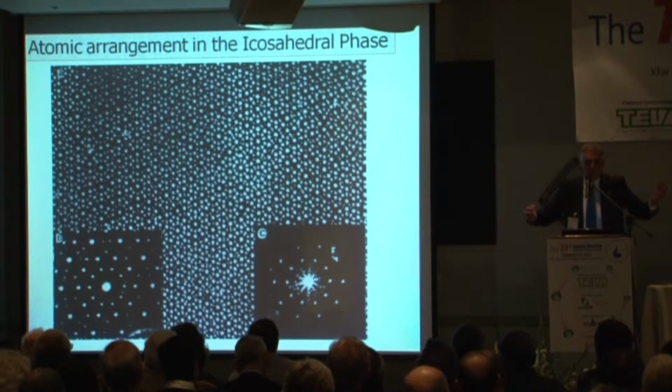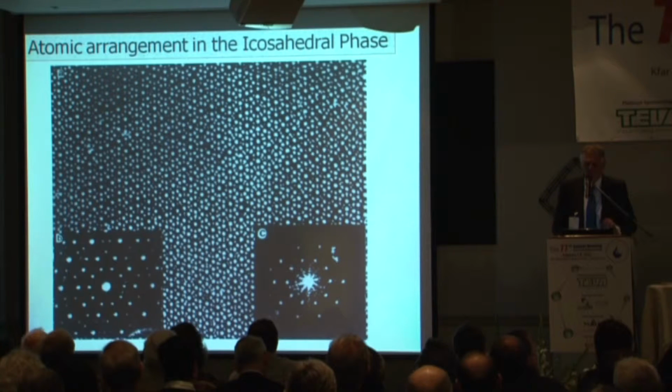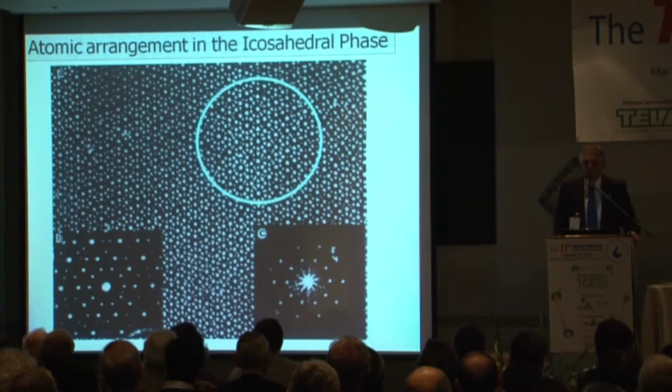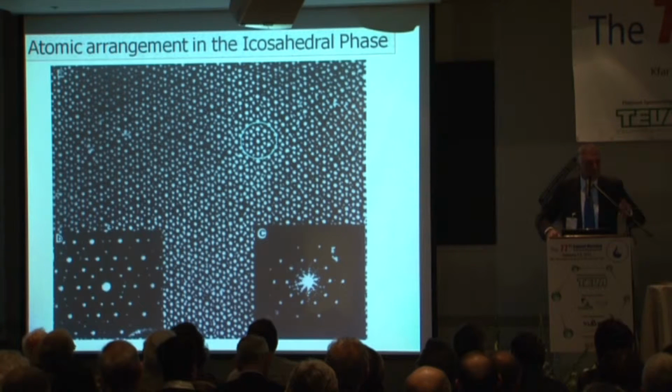So you can say, okay, big deal. Of course they look the same. Aha. But what you can do, and what they did, was to build an aperture and close that aperture closely to see whether this image disappears or changes into a single crystal diffraction pattern. It did not. Anywhere you shrink it to 0, and this image remained, it becomes fainter and fainter, and finally disappears for lack of information. But it does not change. So, no twins, okay?